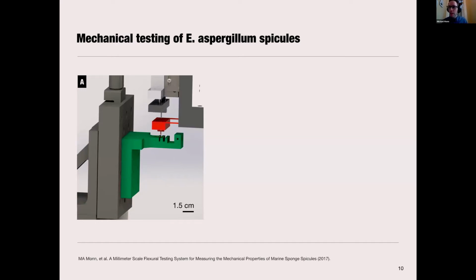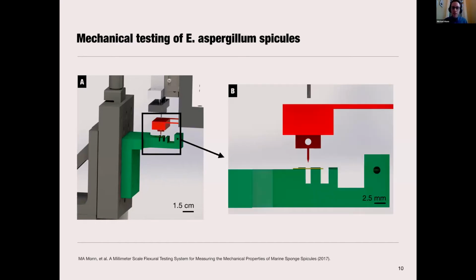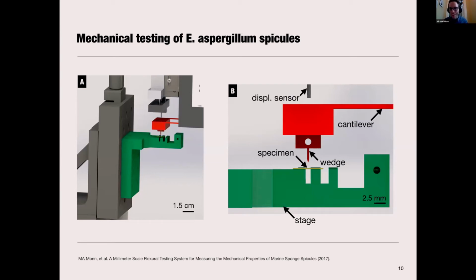And also something much smaller like an AFM couldn't provide the maximum forces that we needed in order to do this. So we basically designed a scaled up AFM. This scaled up AFM has a sample stage that we place our specimen on, and the specimen spans a trench in the stage. Then we come down from above with a wedge, a tip, just like an AFM tip, except quite a bit coarser. That tip is attached to a cantilever that we measure the stiffness of, and the deflection of the cantilever is measured with a fiber optic displacement sensor. So this is basically a homebrew scaled up AFM for doing these flexural tests on micron to tens of micron diameter fibers.